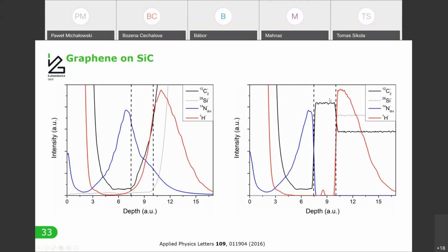So now the dashed lines are actually not needed anymore. You can really see from the carbon signal changes. The intensity is a little bit changed to better show the result, but nevertheless, the result is much better. Now you can see that this organic contamination does not penetrate graphene. We can already see this hydrogen intercalation, which is also very nice to see here, because this is actually a bilayer graphene, where we can see some hydrogen molecules trapped between graphene layers.